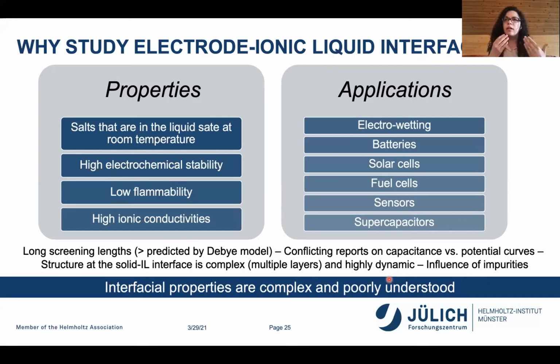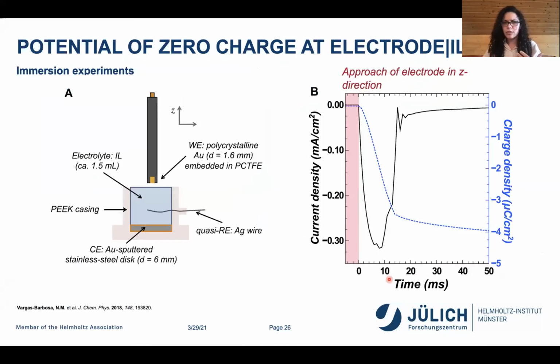So in my case, I said, okay, if the interface is not very well understood, how about we look at one of the most fundamental properties of an electrochemical interface, and that is the potential of zero charge. So for that, we looked at polycrystalline gold electrodes, and we did immersion experiments. We had our electrode here, our pure ionic liquid electrolyte with a quasi reference electrode, and our counter electrode here, at the bottom of the cell. This is all PEEK casing. And all of these measurements were done in an argon glove box. So none of the things here saw anything outside of the glove box. Everything was kept as clean and as pure as possible.